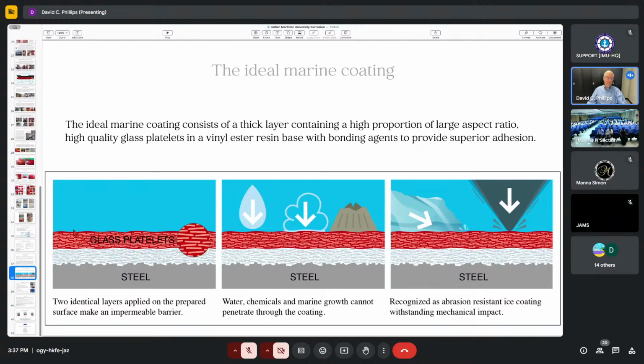If you apply 2 coats, you can go to 3 coats with this coating, with this paint. If you want a really long warranty, or you really want to be sure that 25 years later it's still all intact, you can put a 3rd coating on, particularly for an offshore type of structure that you really can't dry dock. So that's all you get. You get one type of coating. It's in 2 layers. It's applied first one, then the other, to build up a millimeter thick coating of vinyl ester with glass in it.